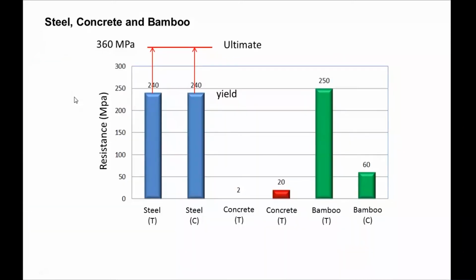If you want to compare steel, concrete and bamboo rapidly in one graph, you can understand that for steel, tensile and compression are equal. For the steel that we use for construction, yield is 240 megapascal and the ultimate is 360 megapascal. For the concrete tensile, it's very, very low. For the concrete, excuse me, in compression, it's 20. And for the bamboo, in tensile we have 250, and in compression about 60. It's a relatively good situation regarding the concrete and the steel.